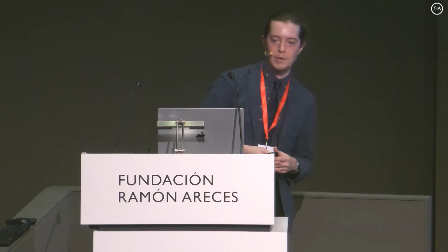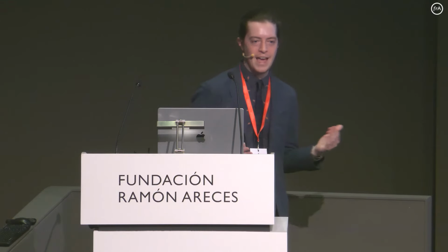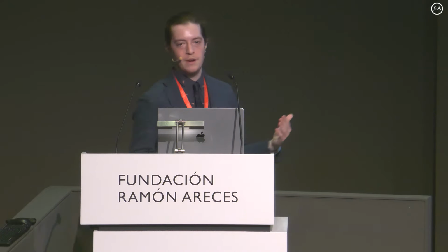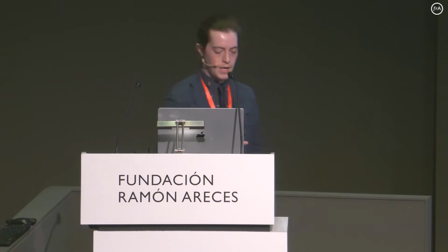So going back to this aluminum-water reaction, we can basically think of aluminum as hydrogen storage. Instead of shipping hydrogen, we might ship aluminum and then react it with water on site to generate hydrogen by this reaction here. And so we can compare the effective storage density and specific energy and energy density of this aluminum-water system to conventional means of storing hydrogen. If we think about storing hydrogen as a gas, the state-of-the-art way to do that is putting it in a tank at about 700 bar. And if we do that, we can achieve a weight percent of 5.4%. So that means 5.4% of the total mass of the storage system is hydrogen.